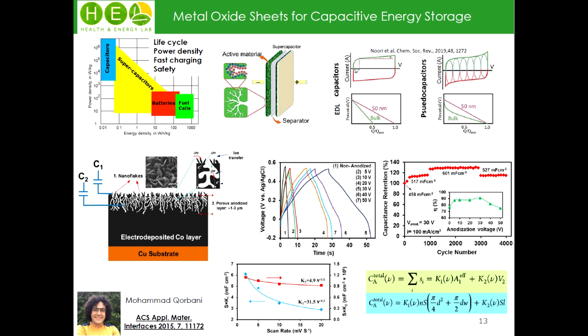One part was the flake-like layer and another was the porous anodized layer. By this model, we realized that, as you can see from the coefficients K1 and K2, the portion of the porous anodized layer was much more than the flake-like structure because of its higher thickness. To increase the contribution of flakes, we should have larger flakes in terms of lateral size than this one.